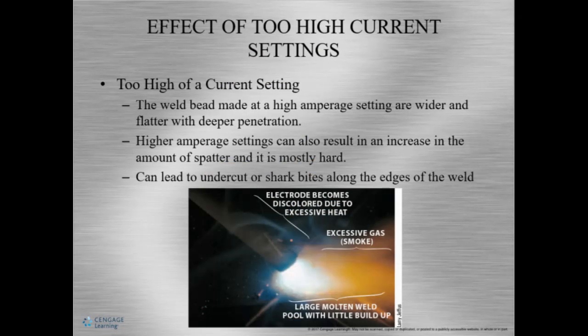Now, what happens if the current's too high? Well, the weld bead will look very, very flat and wide and sometimes kind of sunken in. When the amperage is too high, there can also be a lot more spatter. Having the amperage too high creates more heat, which can create undercut, or they look like little sharp bites along the edges of the weld. An undercut is caused when the arc gouges into the base metal and there's no filler metal being placed there. When it's too hot, not enough filler metal is placed because it's spreading out or it's burning away.